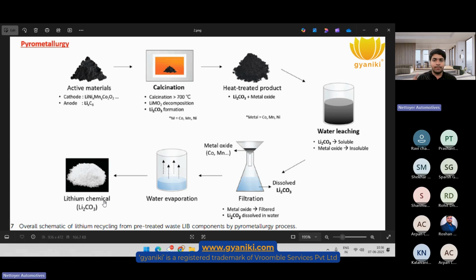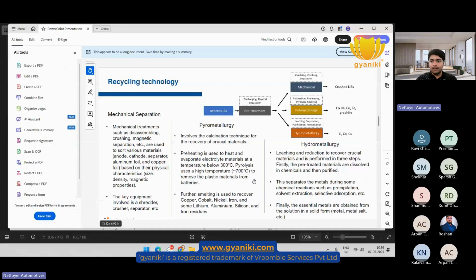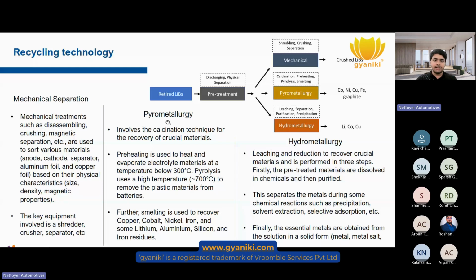But other than lithium metal or lithium metal salt, we have other materials like aluminum, iron, as well as nickel, which are extracted with the help of the same process. Now, taking a look at pyrometallurgy once again, we will understand that it involves a lot of heat. There is a pre-treatment, a post-treatment, and a leaching process with water as well. So it involves usage of heating, that's a furnace, water leaching, and high containers in order to extract the overall lithium. Because there is heating, there is a chance that all the materials might get stuck to the crucible, and things cannot be handled at 100% efficiency. So the efficiency for pyrometallurgy is limited, and how do we improve that? That's another topic, improving pyrometallurgy's efficiency as well.